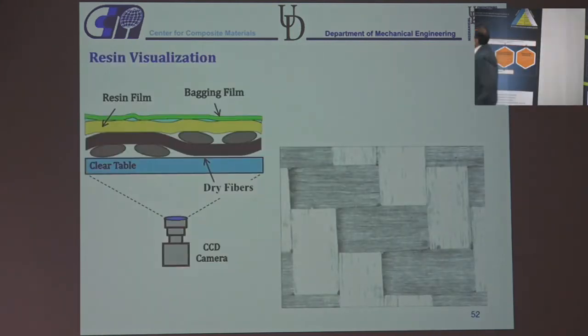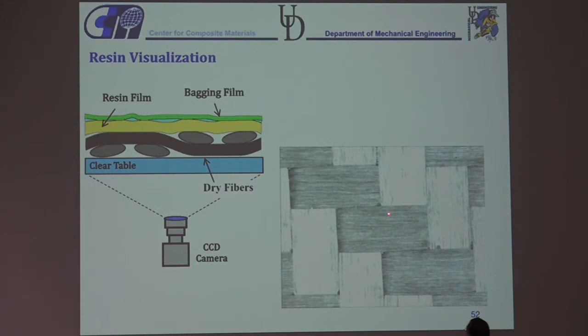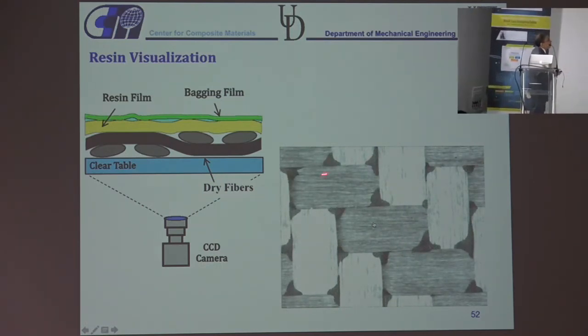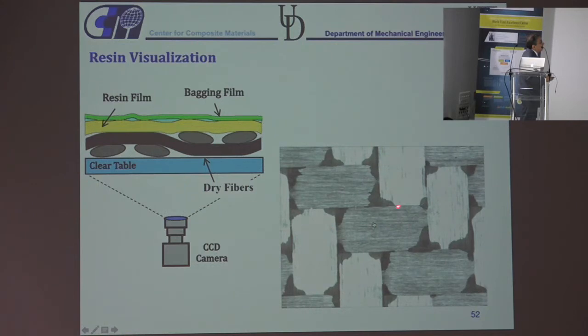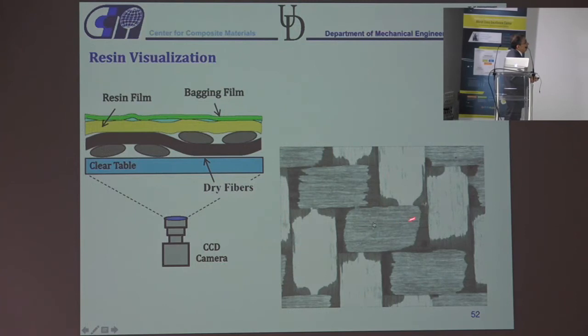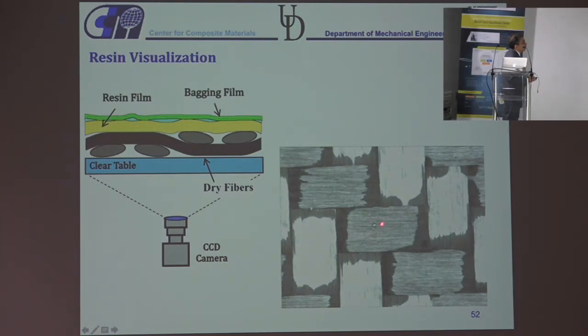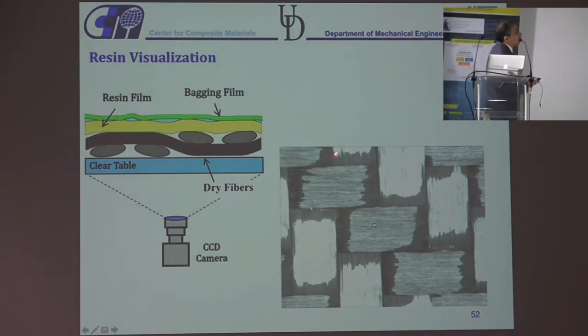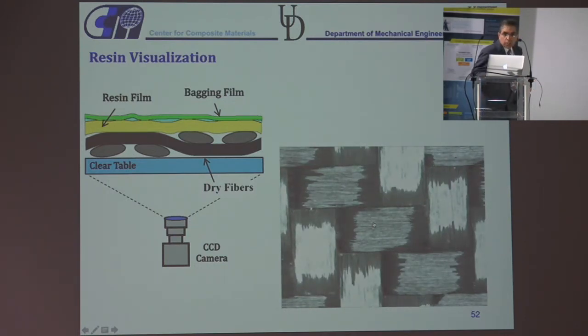Okay, so that was one other thing that happens, is that as you can see, hopefully the video will work, but there is a resin film on top, and as you compress that resin film, you notice that the resin comes in through those pinholes and then starts to spread into the tows. And again, that has the ability to capture the voids, and the size of the pinholes will again introduce all the variability that happens in here.